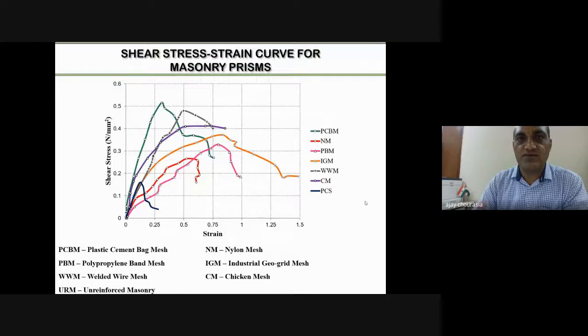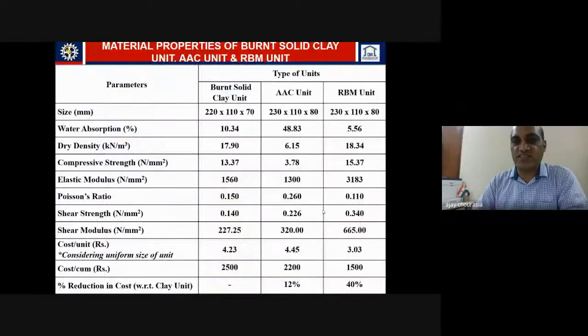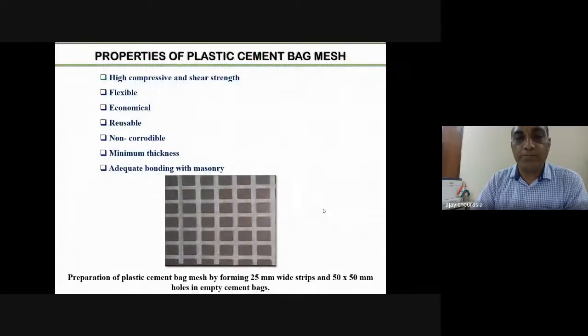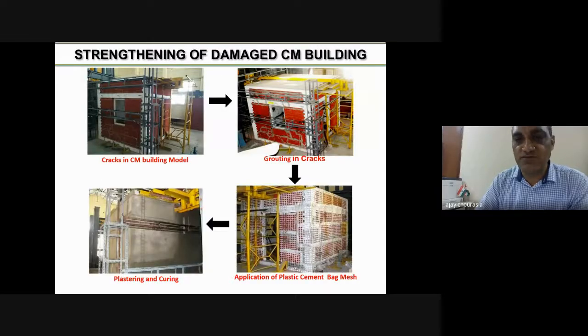Based on that, it has strengthened our belief that in these preliminary tests, we have enhanced the strength of masonry substantially using the plastic cement bag jacketing approach, and why not adopt this particular approach for further investigation and retrofitting of damaged confined masonry models. The basic reason for choosing this option was the properties of plastic cement bag mesh: high compressive strength and shear strength after jacketing, flexible, economical, reusable, non-corrodible, minimum thickness, adequate bonding with masonry, and keeping these features in mind, the further investigations were performed.